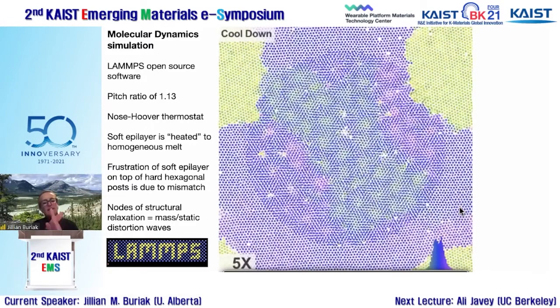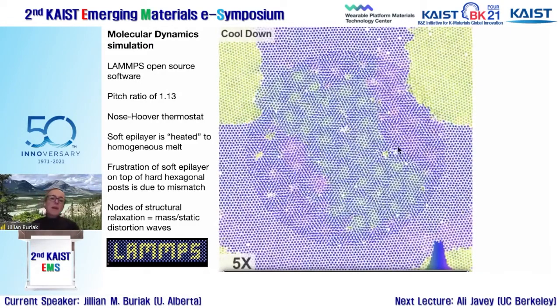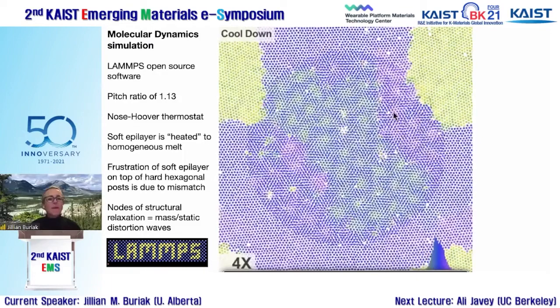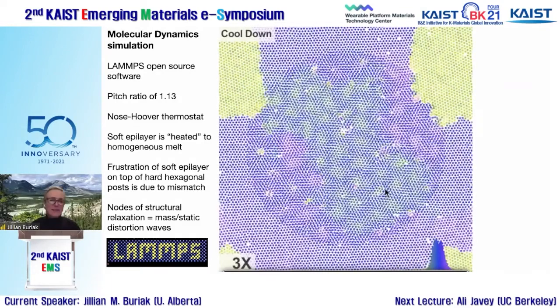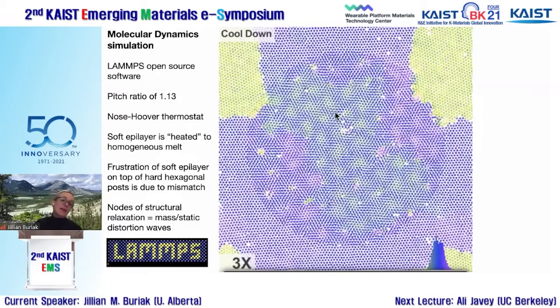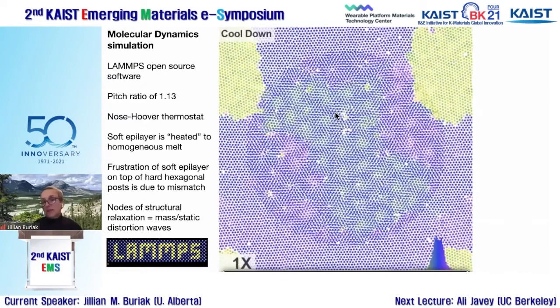So this is a plus or minus 11 degree rotation. We're cooling the system down, and it's giving us a motif that is very similar to what we saw experimentally. And so once you have a model, then you can actually use that to try to pull out what's going on with respect to the interaction of the soft material with the soft material, and the soft material with the hard material underneath, to understand the origin of these static distortion waves.